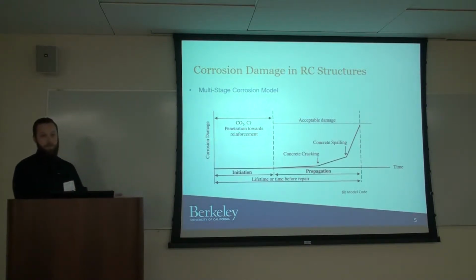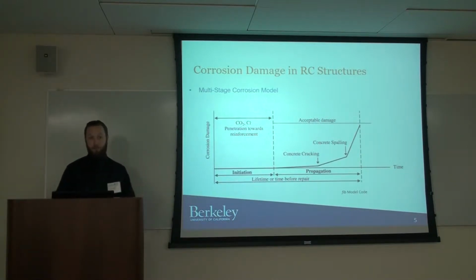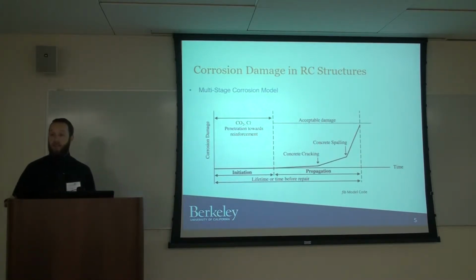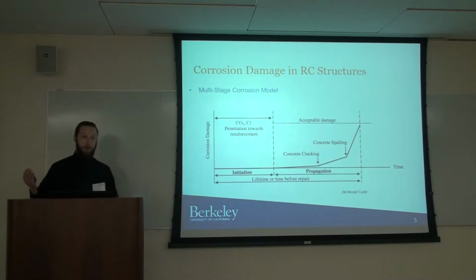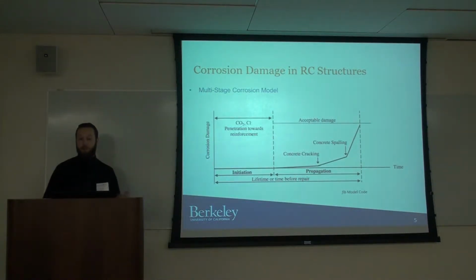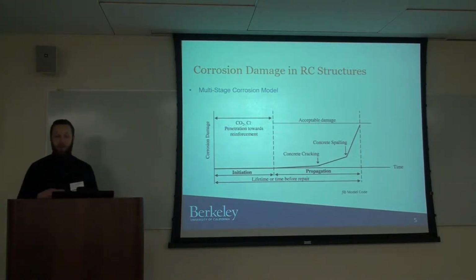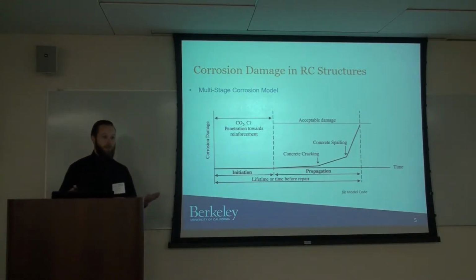during which rebar is actively corroding until you have cracking in the concrete, at which point the damage is accumulating at an accelerated rate. You eventually reach spalling of the cover, and then at some point you reach some acceptable limit where the structure either has to be repaired or replaced.